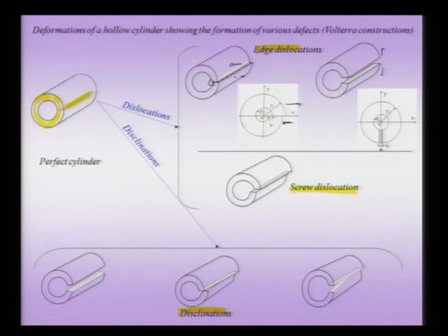In the case of screw dislocation, you do not push and pull the way it has been done here, you actually slide one part, that means you pull the upper part and shear the lower part. So, it is some sort of a shearing motion. You apply a shear on the cylinder, one on the top and the bottom, to create a step which is here, and correspondingly there will be a step on this side also. So, I am using a cylinder, making a cut, and after the cut has been made, I slide one part of the free surface with respect to the other, and that is done by shearing forces. So, I can create things which we shall see have an analogy in crystals, but this is basically the continuum edge dislocation and the continuum screw dislocation.